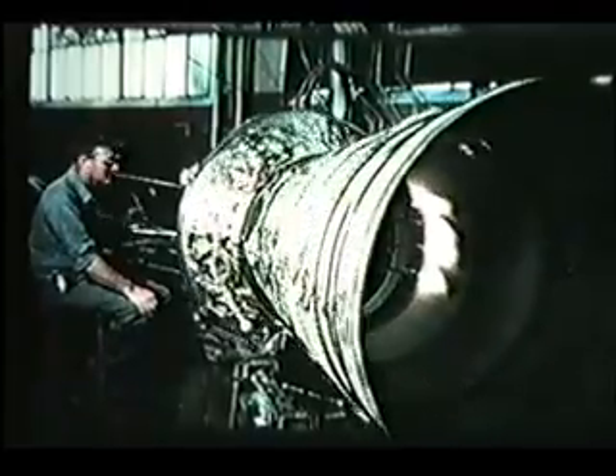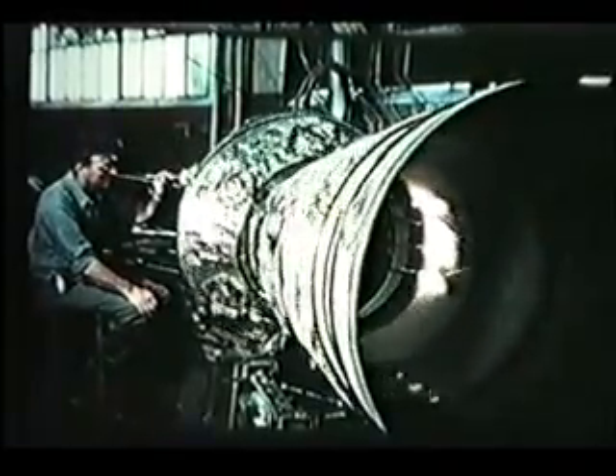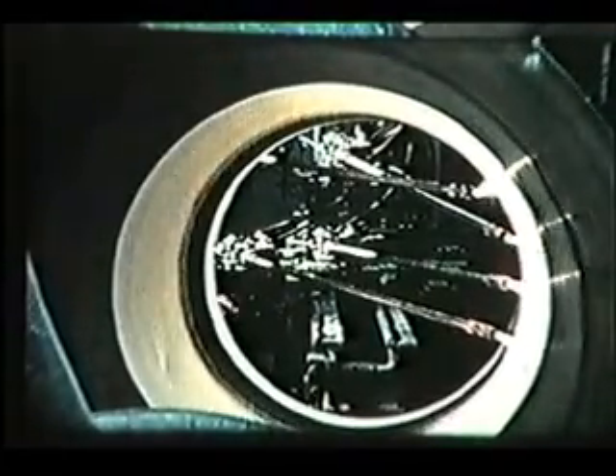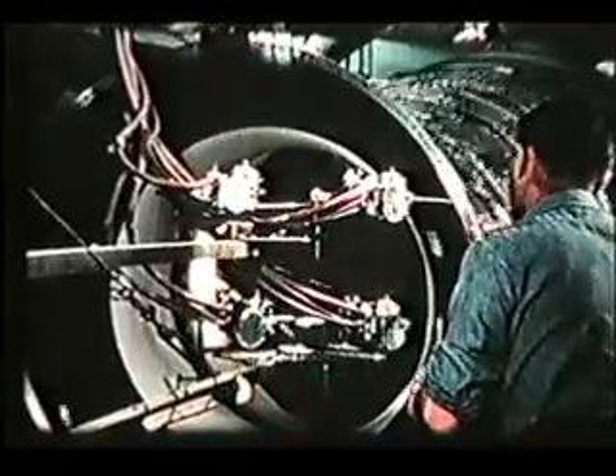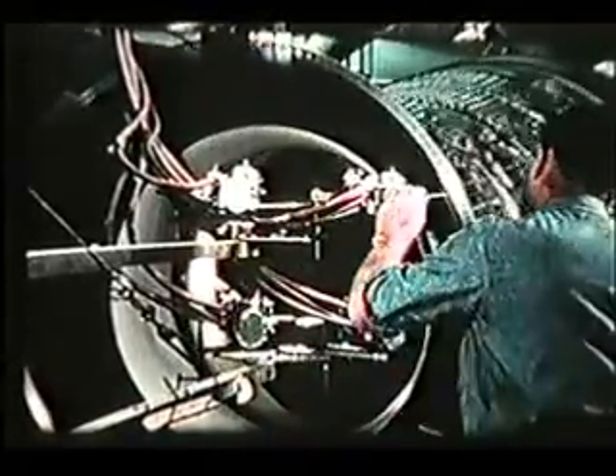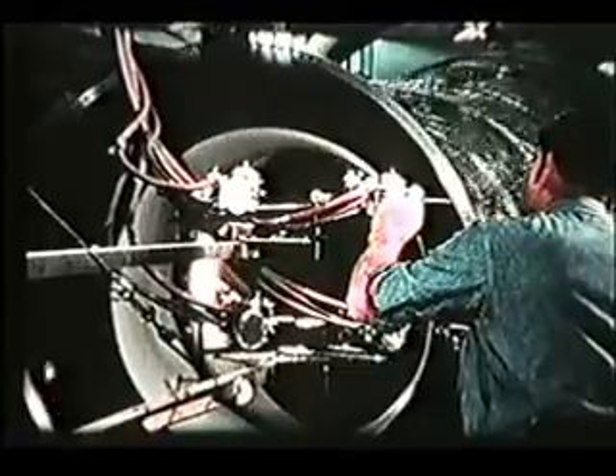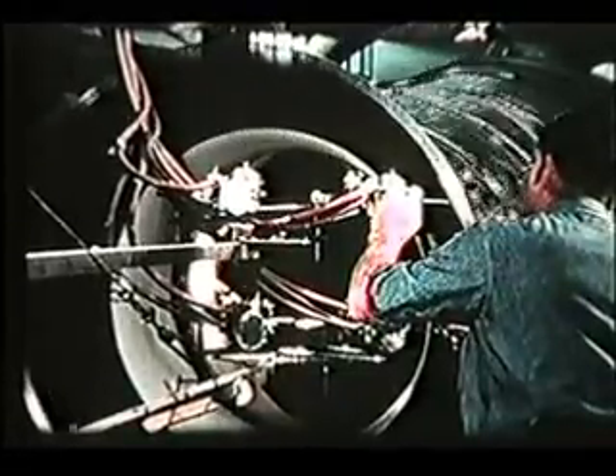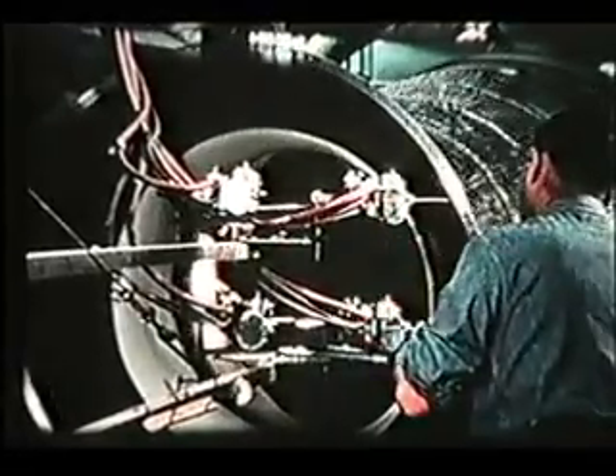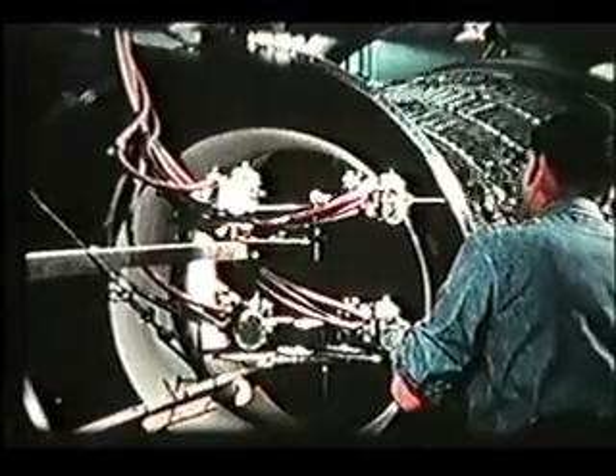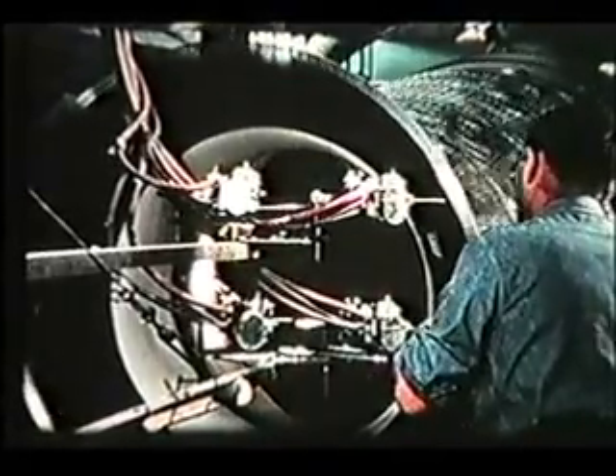Here you see the production coating of a large thrust chamber with a 4-gun arrangement to apply the coatings at minimum cost. The protective Rockide coatings are providing insulation from the high heat and erosive forces of combustion with minimum increase in weight. The 4 guns are seen from the operator end with the gun support arms attached to the traversing mechanism of a lathe. The Rockide Z is being applied approximately 90 thousandths of an inch thick at the throat and being feathered out to 10 thousandths of an inch thickness at the exit end.